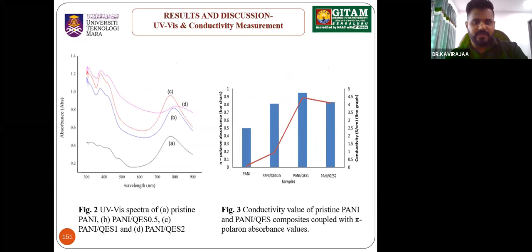Okay, so figure 2, UV-Vis. Here we can just focus on the absorbance peak at 700 to 800 nanometers. Basically, that peak is the pi to polaron transition, which indicates the amount of charge carriers possessed by the polyaniline backbone. The higher the charge carriers, the higher the conductivity will be, as shown in figure 3. As you can see in the figure 3 line graph, PANI/QES1, which means the ratio is 1:1 between PANI and the QES, recorded the highest conductivity in our study, and it also performed the best in terms of the sensor measurement. Next slide.